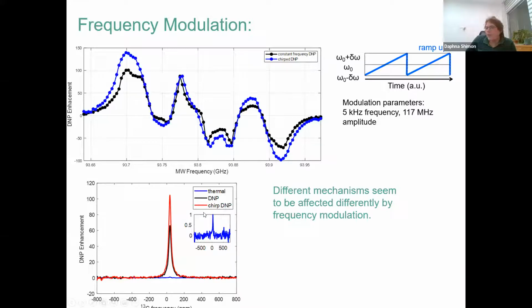The other more important thing is that you can see that the mechanisms behave differently under the modulation. For the solid effect and the Overhauser effect in the center of the line, there's not so much of a change, but there's quite a large change on the edges, and that suggests that the mechanisms are different and that we're not looking at an Overhauser effect here on the side.